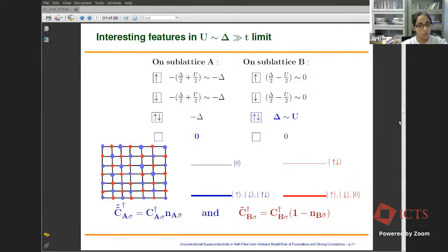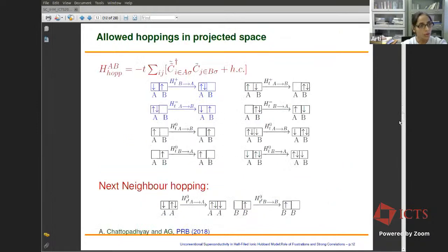So basically one has to work with these projected Hilbert spaces where holes are projected out from the low energy Hilbert space on A sublattice and doublons are projected out only from the low energy Hilbert space of the B sublattice. Now, what happens as an effect of that? So now if you want to do a generalized Schrieffer-Wolff transformation, treating your hopping term perturbatively, because that's the smallest energy scale in your problem, you will see that it is very different from the half-filled Hubbard model, because not all the hopping processes are projected out.